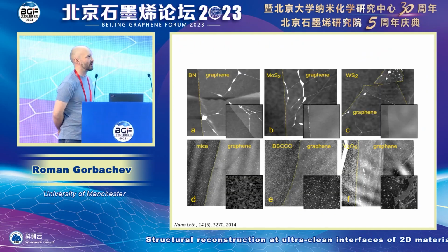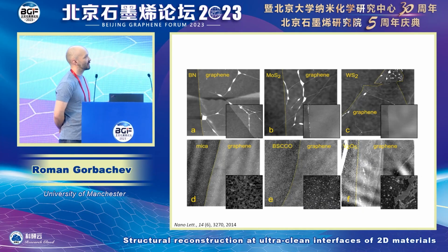The reason we use PDMS is that PDMS is quite dirty, but the real key is that when you stack these materials and you look in, for example, AFM, you see that a lot of area is atomically clean between them. And this is where we get the high mobility. But in between, there are these bubbles and pockets of contamination. And that is the problem for the scale. We cannot scale if a lot of the area is contaminated with these folds and pockets.